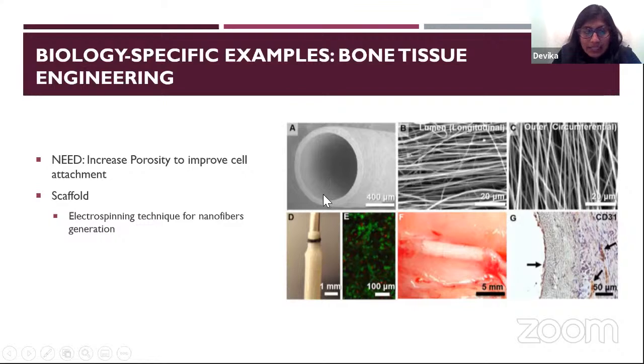So what they did here is that they made nanofibers, and they controlled the orientation of the nanofibers, meaning that on the surface they had a circumferential orientation. That means it's going in circles around, and along the inside of this graft they made it longitudinal. So what this actually did was it promoted a specific type of cell on the outside and a specific type of cell inside. The inside of the graft had more endothelial cells, so blood vessel cells, because that's what the human body has, and they wanted to mimic the real blood vessel. And the outside has smooth muscle cells because they pump. The muscle cells will pump the blood, pump the vessel. So that's the reason why they had these two different kinds of orientations.